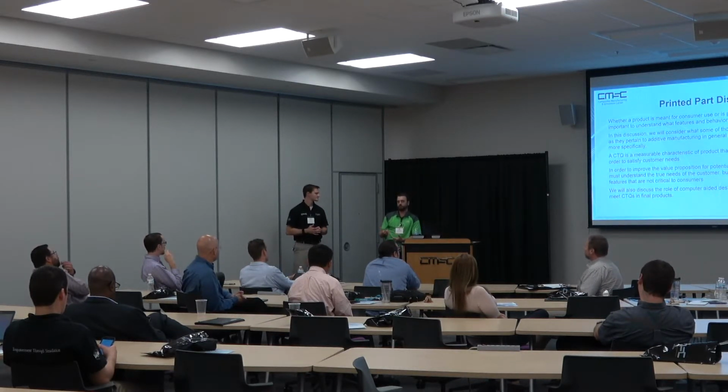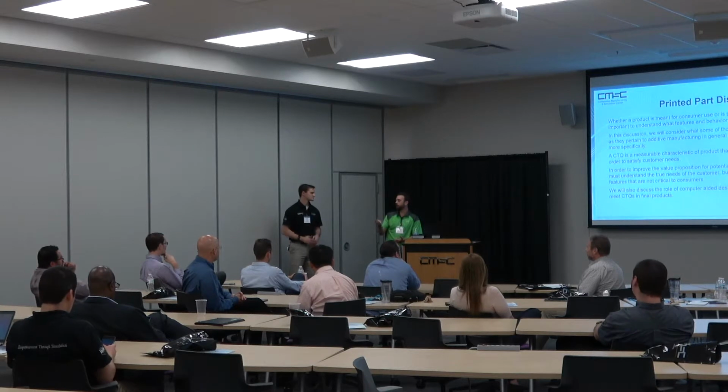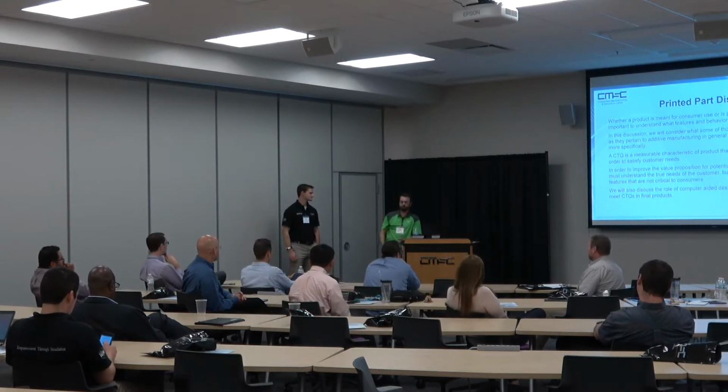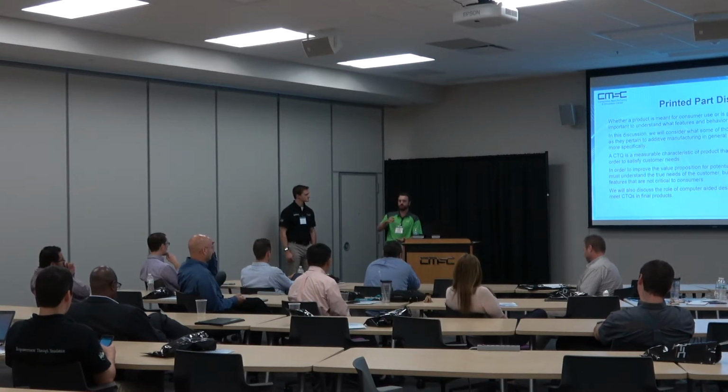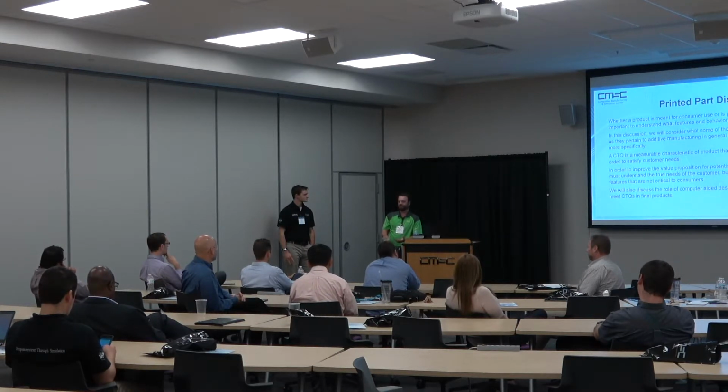And to that, processing standards are really tough. Mike has a BAAM, we have a BAAM. He might run a certain material hotter than we do, and we all saw that bead-to-bead layer adhesion can differ just from how hot you run, or from your tamping device, whether you're using something that's tamping or rolling. You probably get different characteristics of your part if we go 50 degrees hotter than Mike does.